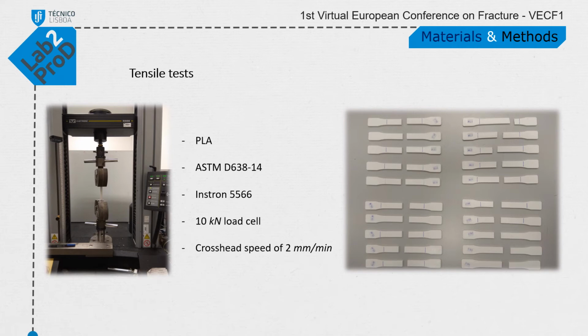The standard test method used follows the specifications from the standard ASTM D638. The tests were performed on a universal testing machine with a 10 kN load cell and a crosshead speed of 2 mm per minute.